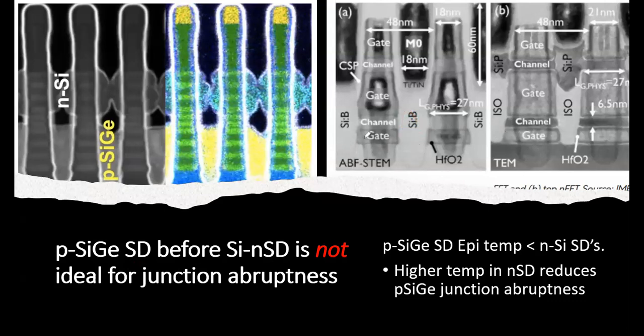Right, here is silicon, but in the future, here is a SiGe. Silicon with boron is fine. But if you move to SiGe as the stressor, the boron diffusion is very temperature sensitive. This means your high temperature for the N source and drain, which is silicon on top here, the temperature for forming source and drain is a silicon SiP process, which is reasonably high temperature.